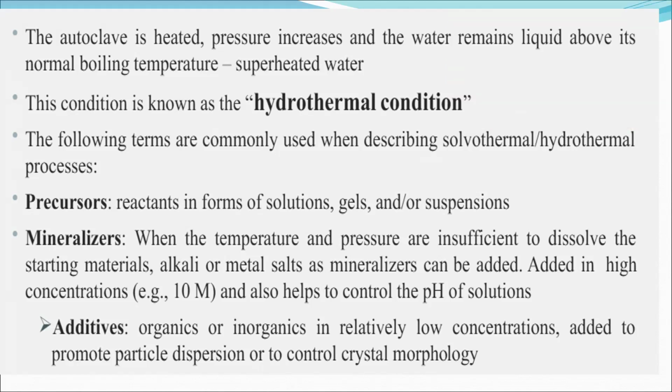So during the process, when the temperature and pressure are insufficient to dissolve the starting material, mineralizers, alkali or metal salts, can be added in high concentrations, of around 10 M, which also helps to control the pH of solutions. So that's what mineralizers are. Then additives. These additives are organic or inorganic, in relatively low concentration, added to promote particle dispersion or to control crystal morphology.